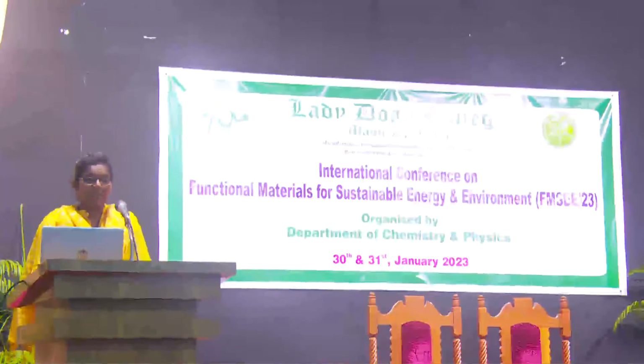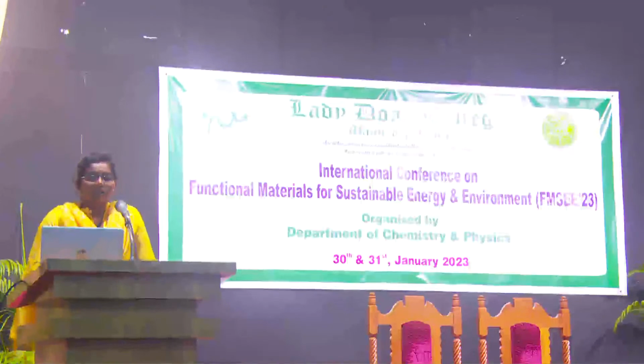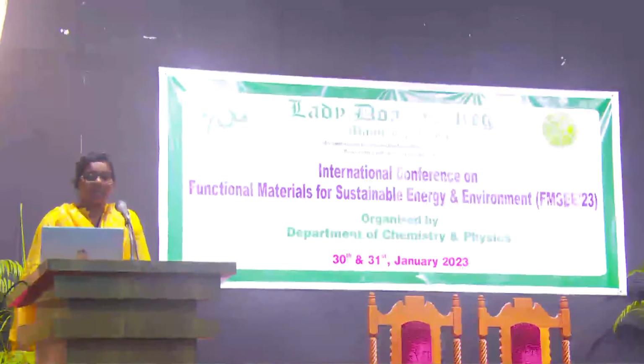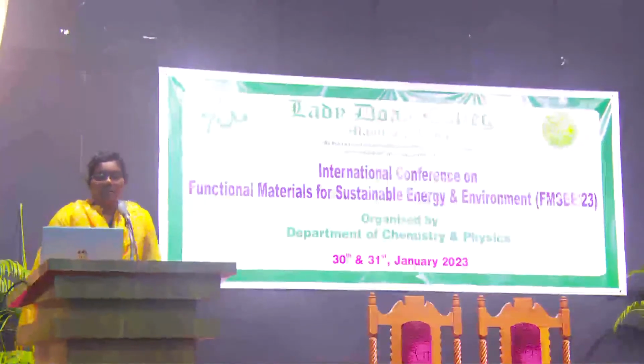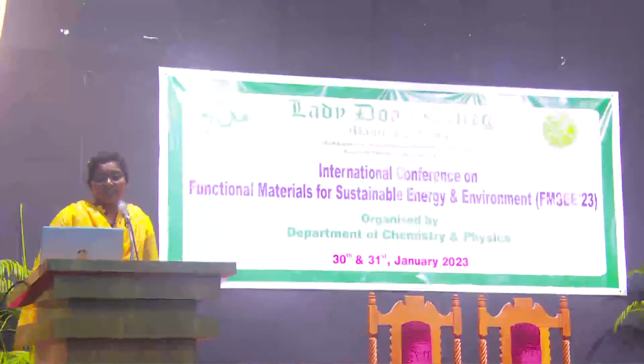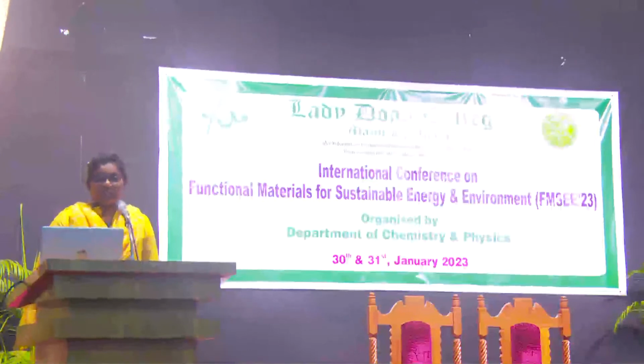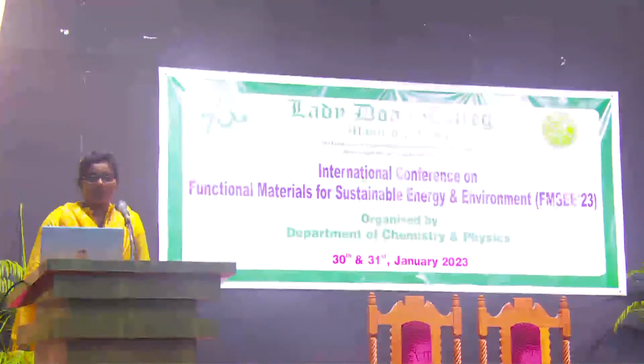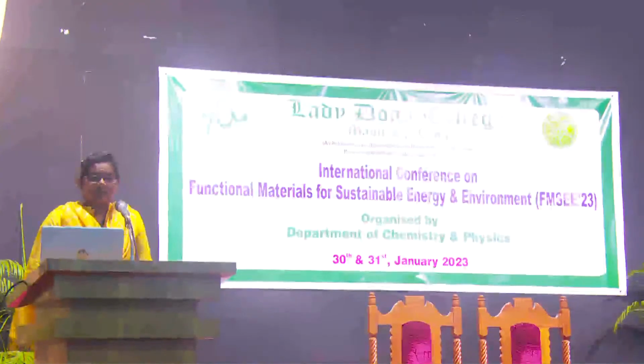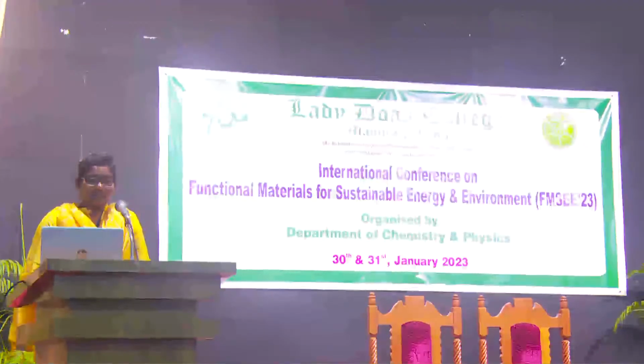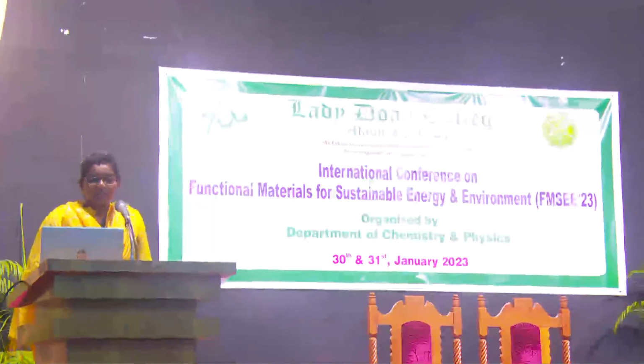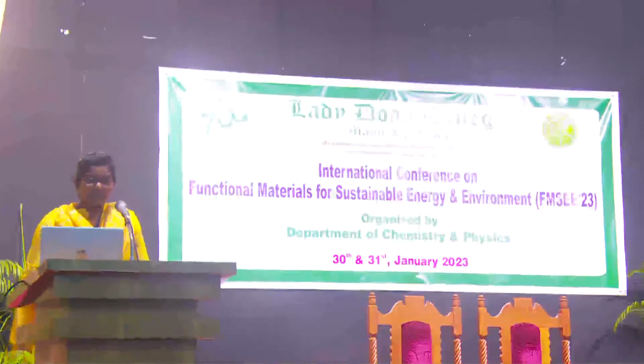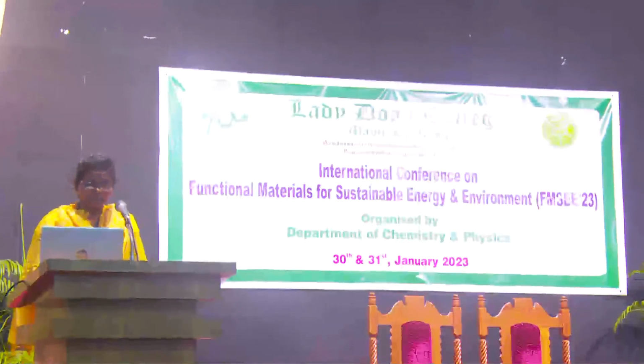And preparation of my polyvinyl alcohol: taking PVA plus distilled water, with continuous stirring, I have obtained PVA gel. For organic dye preparation, I have extracted from the Basella alba plant and extracted the organic dye and added some ethanol, continuously stirring at room temperature and at 50 degrees Celsius.